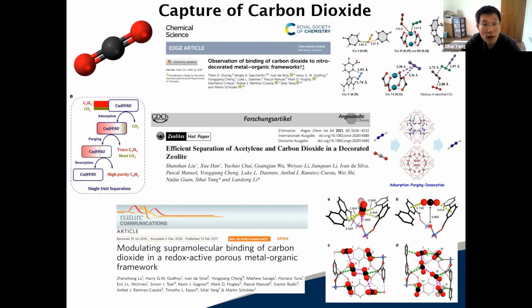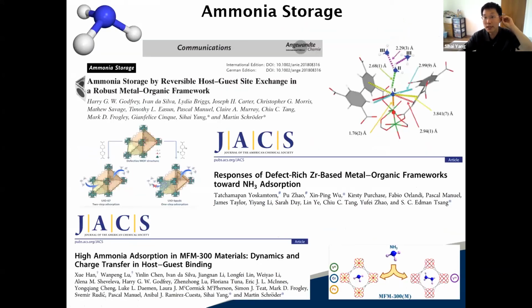So if we look at the capture of carbon dioxide in the porous MOF, in terms of functionalization with a nitro group, we visualize the interaction between the CO2 and the interior of the MOF, particularly the functional group and also the redox active metal site in the MOF material, and how they contribute to the strong absorption of CO2. And of course, on the zeolite, we dope metal ion into the zeolites and then look at the binding between acetylene and the CO2. So clearly, neutron diffraction and scattering played quite an important role in distinguishing between the acetylene and the CO2 molecules.